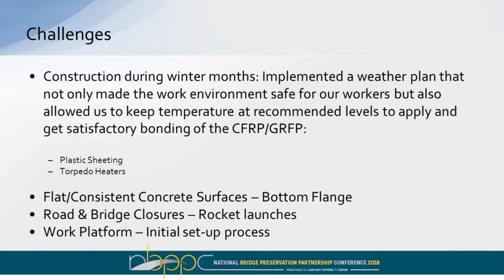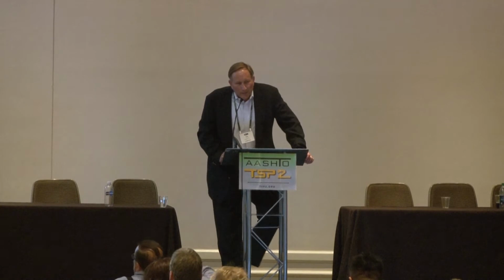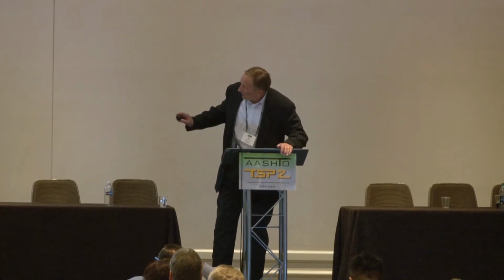So some of the challenges that we had with this project, we unfortunately got a little bit of a late start, and so that took us into the late fall, early winter, and of course in this part of the country it does get fairly chilly at night. So one of the things that we needed to implement was a weather plan that made the work environment, one, safe for our workers, but also allowed us to keep the temperatures in the areas that we needed to work at a decent temperature in order for the carbon fiber, glass fiber to bond. And typically most suppliers of these materials recommend something right around the 55, 60 degree surface temperature mark in order for those resins and carbon fabrics to set up and form and sit in place.